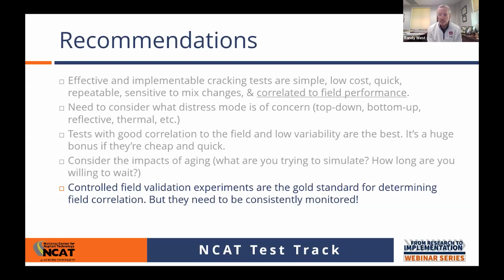And you're going to see for your materials, your data for whatever cracking test will be different than what we show. So if you're going to set a criteria, it needs to be based not on NCAT's data, it needs to be based on your own data. The real negative with doing those field experiments is you're going to have to wait a while to see the results. And it may be 5 years before you have results that are meaningful between what works and what doesn't work in terms of mix cracking resistance.